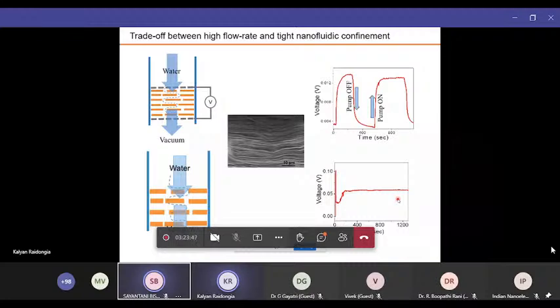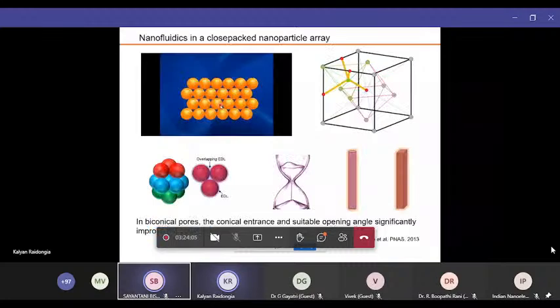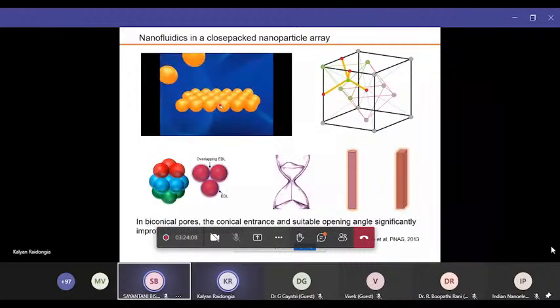If channels are large, liquid will flow very fast, but nanofluidic confinement will not be there. The overlapping of the Debye layer will not take place, and because of this, we will not get any energy, because without overlapping Debye length, nothing will happen. So therefore, we can go for an alternative system where we can assemble a large number of monodisperse spheres one upon another.